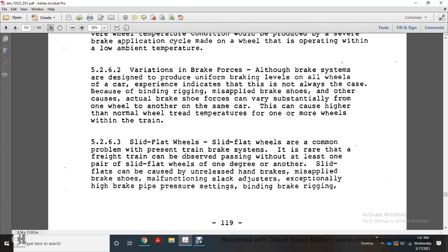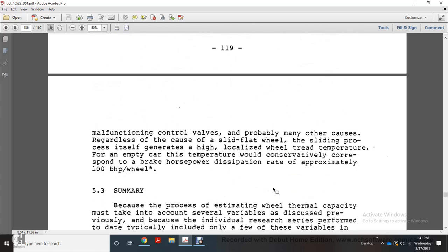Slid flat wheels. Slid flat wheels are a common problem of the present train brake system and the rail freight train; few trains pass without at least one pair of slid flat wheels, to one degree or another. Slid flat wheels can be caused by unreleased handbrakes, misapplied brake shoes, malfunctioning slack adjusters, excessively high brake pipe pressure settings, binding brake rigging, malfunctioning control valves, and probably many other causes. Regardless of the cause of the slid flat wheels, the sliding process itself generally produces highly localized wheel tread temperatures.